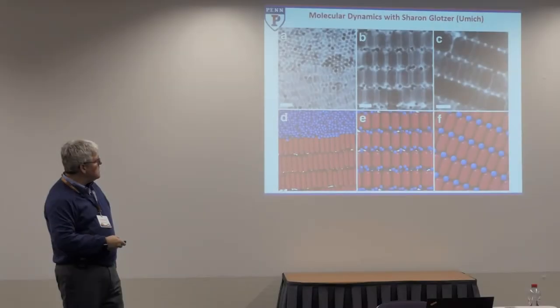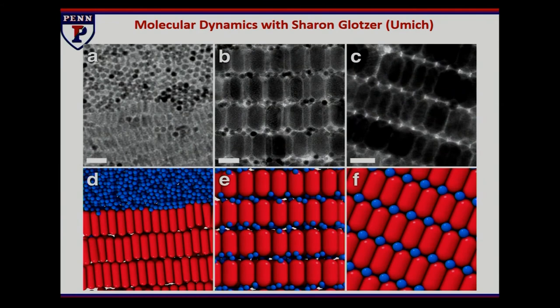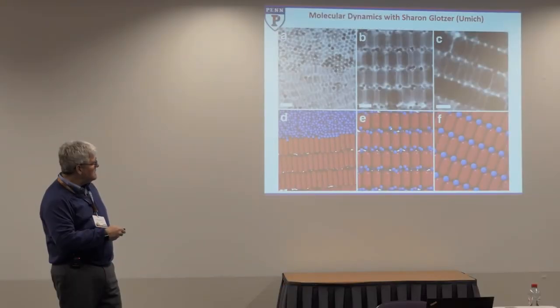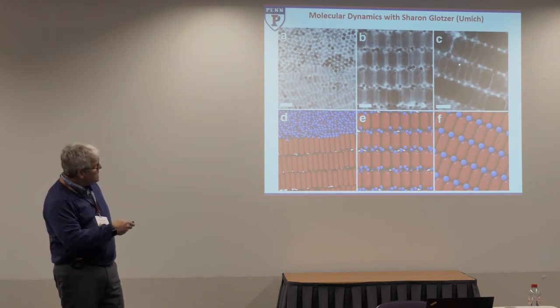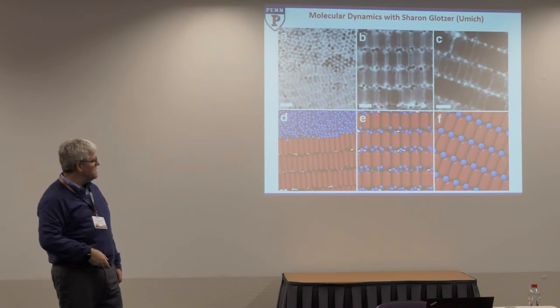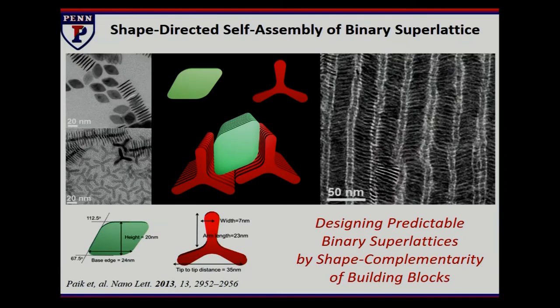If the system is one where the size ratios are too far out of the optimum, you get phase segregation. If the rods pack very nicely, but the sphere particles are too small to uniquely occupy each of the interstices, you get a system that is sort of ordered in one component and disordered or almost liquid-like in the other. And finally, when you get that lock and key matching where just one particle sits right in the void space between the ends of the rods, it locks into a crystal structure. But now it's one that captures two of the most ubiquitous sort of geometries in nanoscale systems, rods and spheres. So you have a chance to think about that modular design aspect again in terms of putting some of these pieces together.